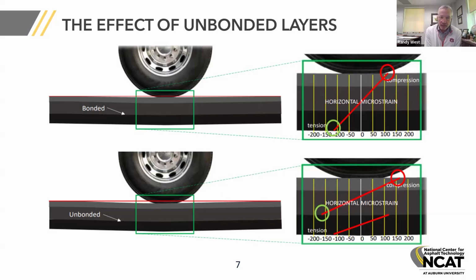So you're getting a higher deflection with an unbonded pavement. That higher deflection is indicative of higher strain in the pavement structure, and that strain is going to lead to cracking.